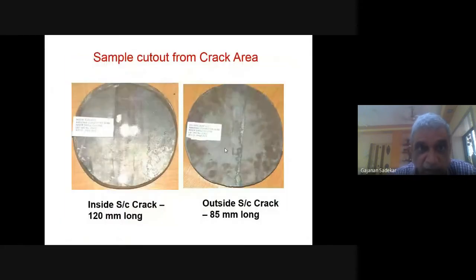Okay. So what we did in this case, because it was not possible to work this equipment, it was decided to cut a sample around that. A repair in process was not possible because the crack was throughout. So we decided to take out the portion of it.